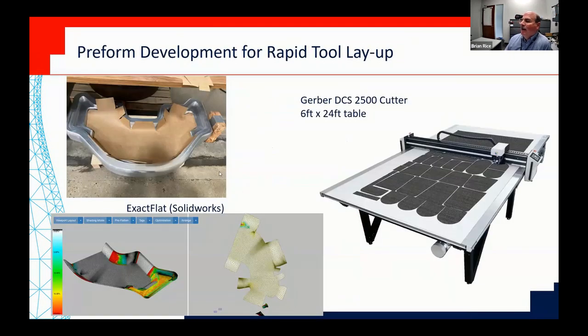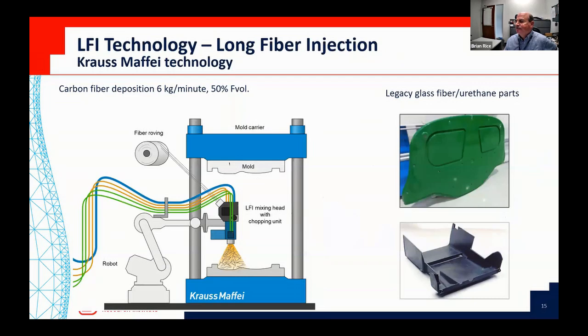the test. And then in terms of, again, trying to optimize automation and reduce time for ply layup and that type of thing, these kinds of parts are typically machined from aluminum because, frankly, the labor to do hand layup with pre-preg is very time consuming. It makes the parts very expensive. So we're showing using the latest software for ply flattening and Gerber cutter and designing the layup not just for the mechanical properties, but also ease of layup allows us to make something like this affordable using composites versus typically what would be an aluminum structure.